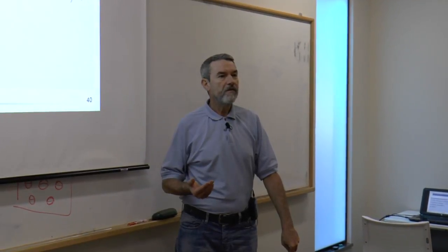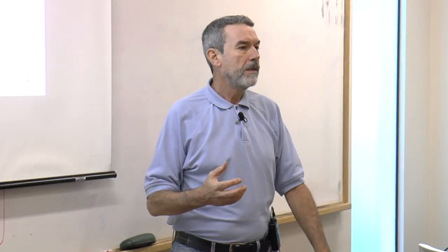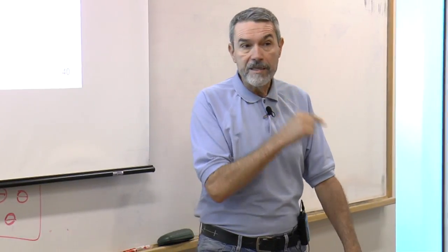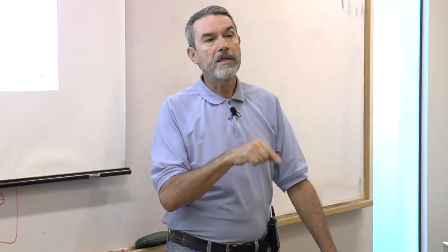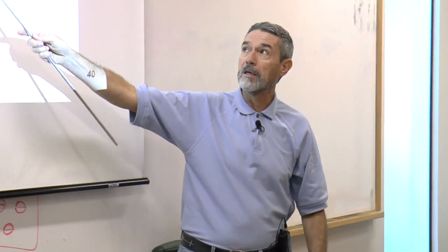We are using viscosity. We are assuming that whatever molecular rearrangements take place in viscous flow are the same that take place in nucleation. But that's an assumption. We don't know that for sure. So maybe the problem is here.